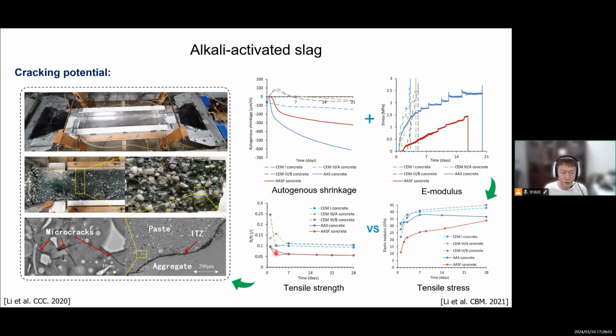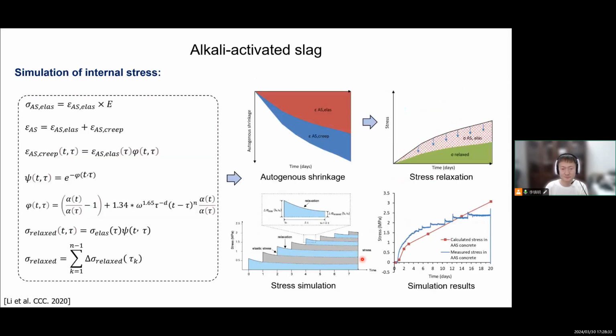So although the tensile strength for alkali-activated concrete is lower. For Portland cement concrete, we know that it's around 0.1. So when you have a compressive strength of 10 megapascal, the tensile strength should be 1 or around 1. But for alkali-activated concrete, it's lower, 0.05. So it is not so good for the cracking because the tensile strength is lower. But thanks to the relaxation, the cracking time is not so early.